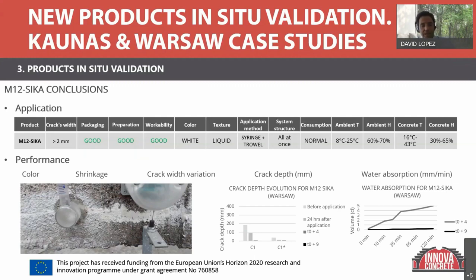Well, as you can see here, I'm showing only the crack depth and the water absorption. Here we have a clear decrease in the crack depth, and we see that after 4 months and after 9 months, it's almost zero. Now, the measurement that we take.